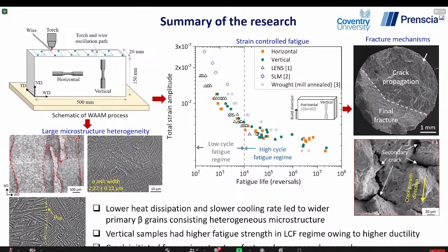And compared to the AM built materials, we have similar properties compared to LENS, and lower properties than SLM. That's mainly because SLM has a martensitic fine microstructure. We have observed that all the samples tested in this program have crack initiation from microstructure features, and we did not find any defects. That confirms that we were able to build a very dense material with a high quality wire.